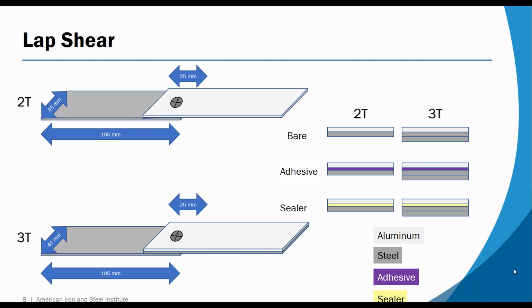That was because of considerations for galvanic corrosion, and that is important in our 3 thickness joints because in the 3 thickness joints, we actually pulled the top sheet and mid sheet together. And that means that for the strength performance of the joint, they do not benefit in any way from the adhesive or sealer. We're actually using them as more of a noise factor to understand how well the joining method works to join the 2 steel layers with an aluminum layer on top, and how much the adhesive might be a detriment to the process.